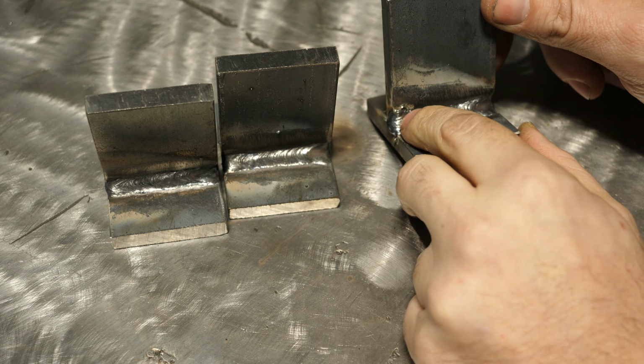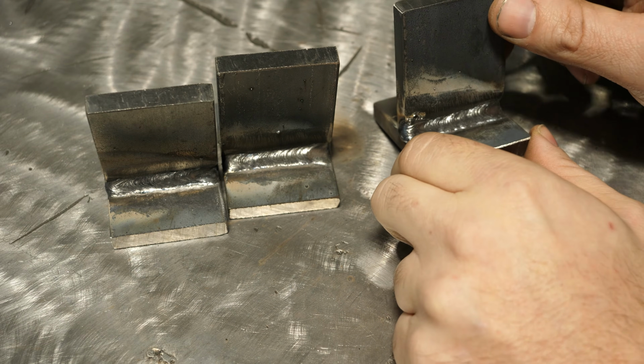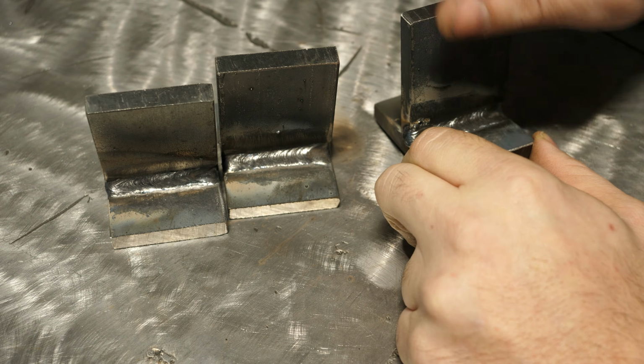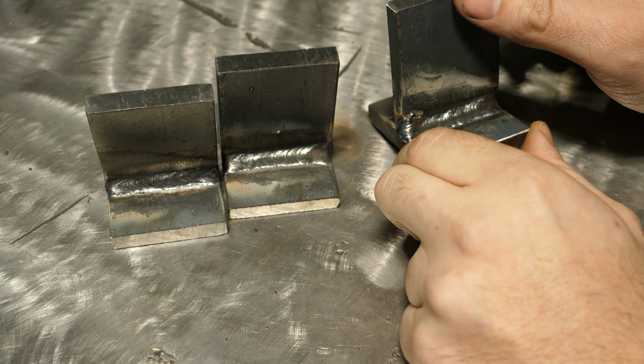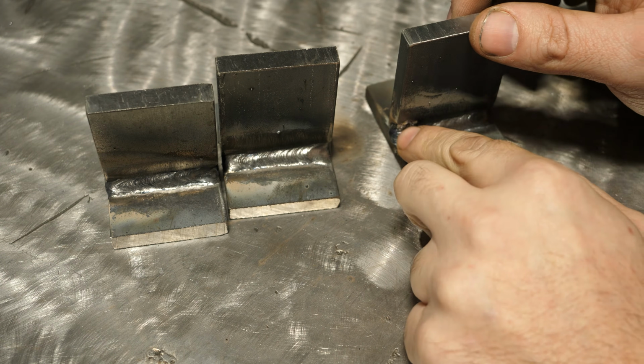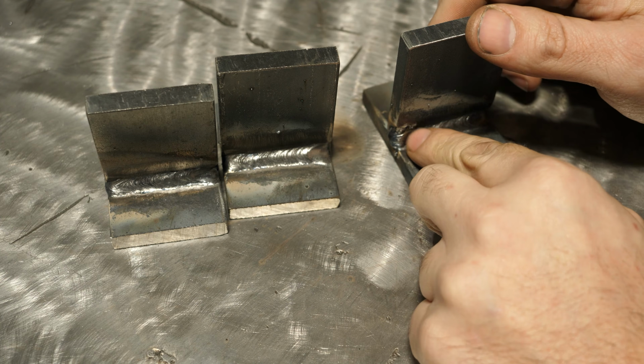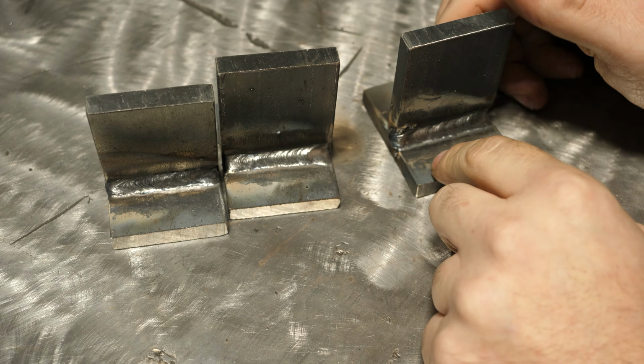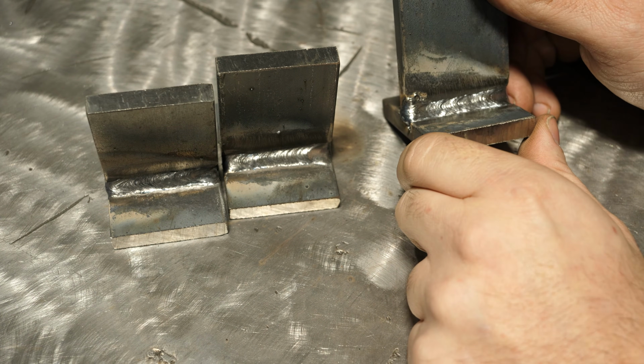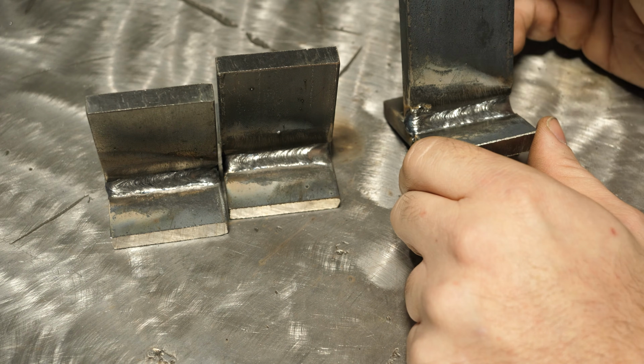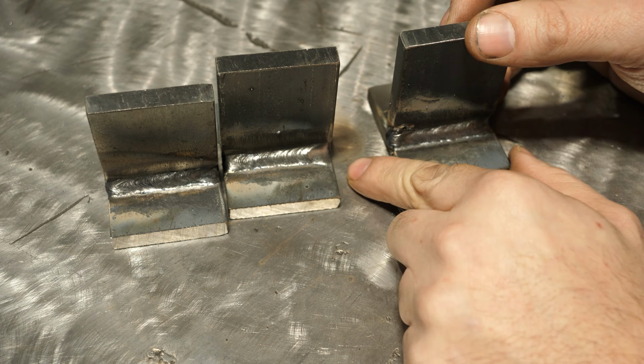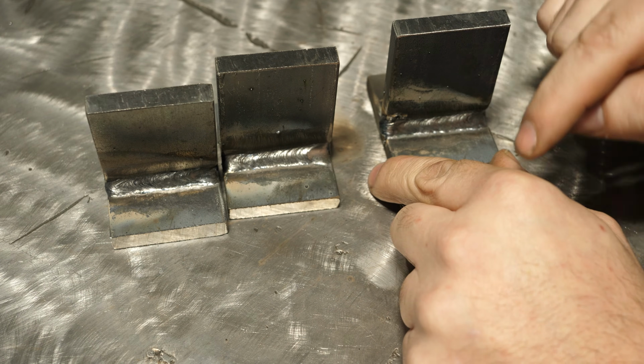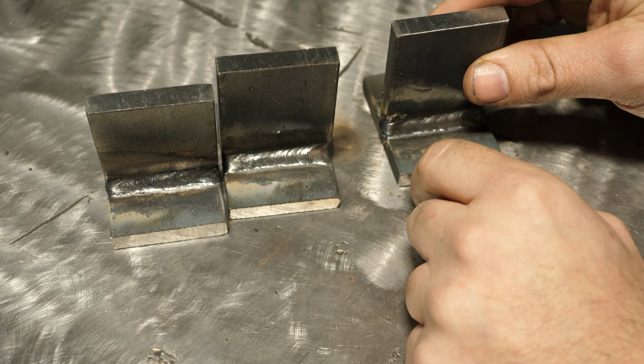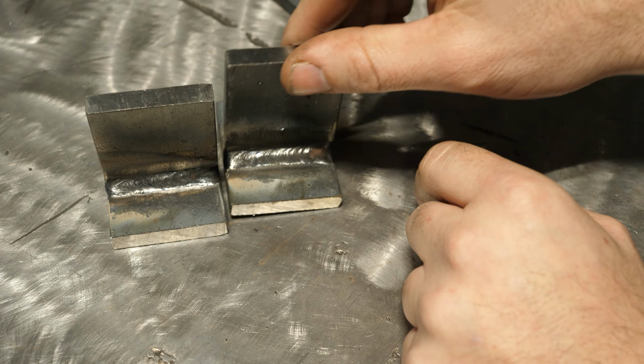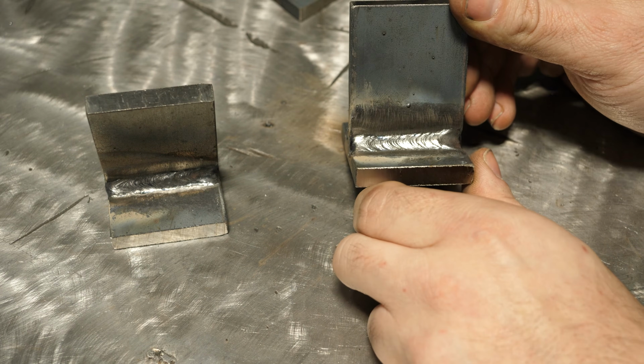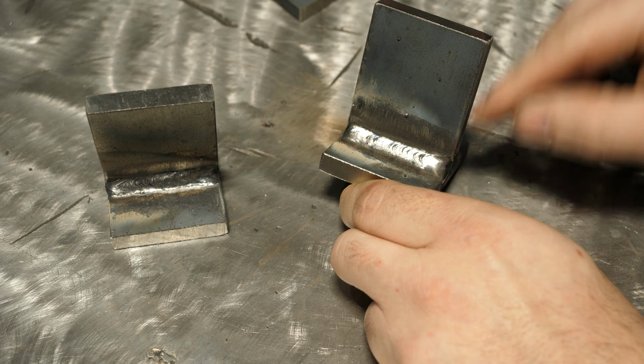When you have an arc strike up above where you weld, as this gets bent, it can create a spot for a crack or a tear to propagate from. And depending on the steel, it will also harden that area, which is undesirable. So this one is still acceptable for what we're going to do, but it's not perfect. This one I am going to bend towards the face, because that arc strike will be less of a concern then.